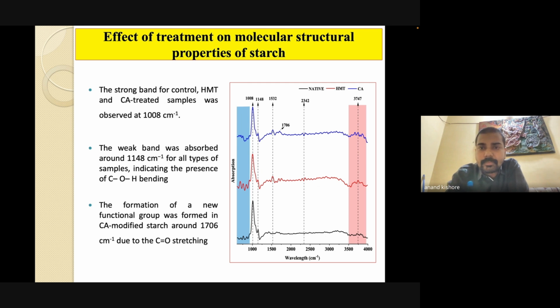This is the molecular structure based on the functional groups. We found no major difference, but we found one peak at 1706, the formation of a new functional group in the case of CA modified starch, maybe due to the citric acid cross-linking.